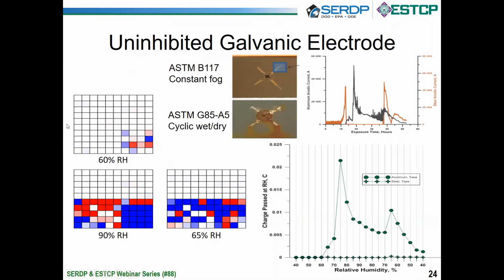I'm going to move on to talking about aluminum alloys. What you see in these pictures are images from two different exposure techniques. This is the standard B117 continuous fog, and this is G85 A5. This is the cyclic technique with a much more dilute solution, but it's pH'd at about 5 instead of being allowed to be neutral, around 6.5 to 7. These are aluminum panels with a stainless fastener through the middle. You can clearly see the difference in behavior from this continuous test to the cyclic test.